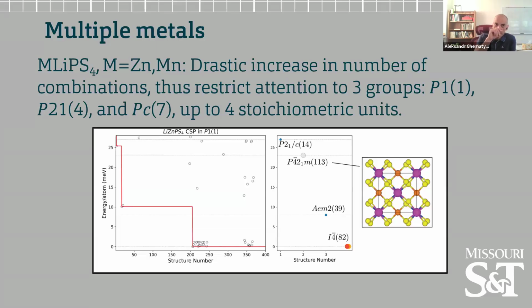So I'm looking at two different metals, zinc and manganese, and in this case, there is a drastic increase in the number of combinations, to an extent that I really cannot do what I have done for the lithium PS4, which ran on the scale of 60 or 70 different space groups. In this case, we limit our simulations to 3 different groups and look up to 4 stoichiometric units. Of course, the structures that we found as a result of the simulations can be in a higher group setting by virtue of the fact that symmetry will come into play when the lowest energy system is found.